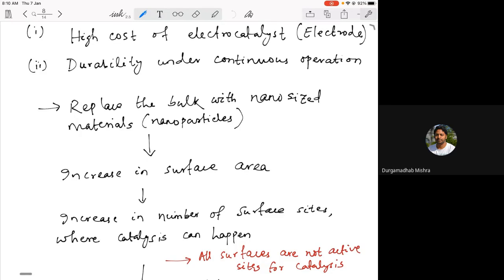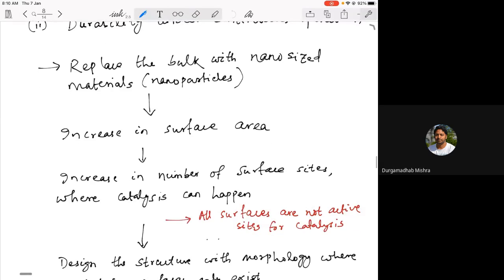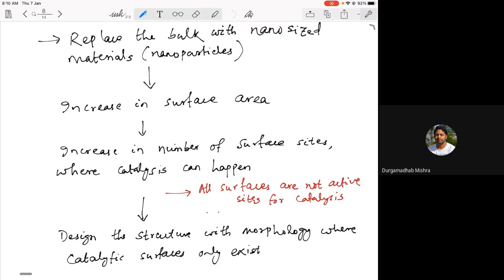And it has also been observed that you can reduce the cost as well as increase the efficiency. However, when we talk about the catalytic properties of the surface, it has been observed that not all surfaces act as an active site for catalysis. These materials have crystallographic planes, like we saw, 100, 111, so different planes, and different planes have different catalytic properties.